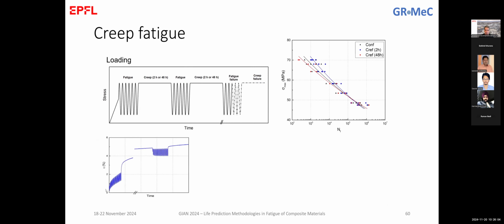You see also the strain evolution. This is the strain evolution during fatigue, and this is the strain evolution during creep, resembling the creep test that we had before. And then continuously changing this, again fatigue, and then again creep, and so on. You see here an effect that we discussed yesterday. Now you remember we said that when the material is left unloaded or even loaded, it restarts the testing at a lower strain. And this is exactly what we've seen here. Even for creep, we had cases, especially when creep was at 2 hours and not 48 hours, that the strain of the specimen, when we were resuming the fatigue testing, was lower than before.